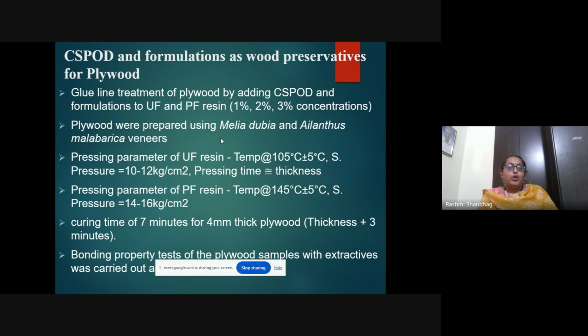In case of wood, you can use the preservative directly, but in case of plywood or the panel product, it is the glue line treatment. Plywoods are made with an adhesive material, which is actually PF resin or UF resin, mostly used in the industry. We mix this preservative along with the glue line, with UF resin and PF resin. We prepare concentrations of 1%, 2%, and 3%.